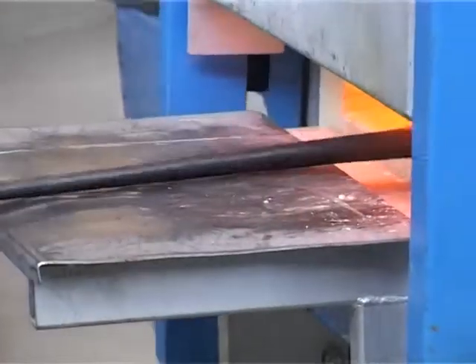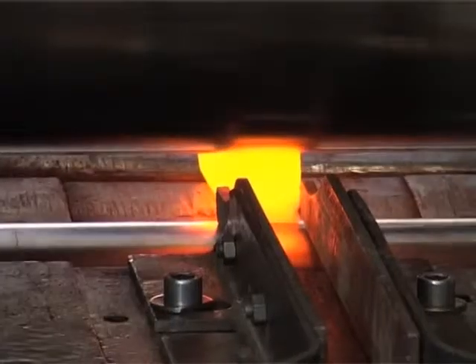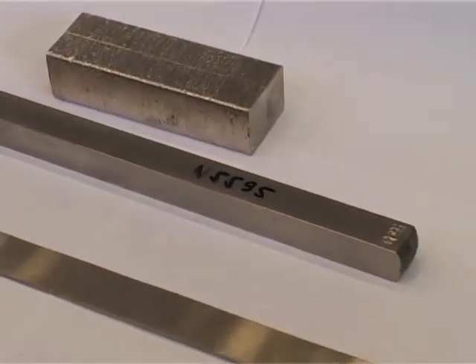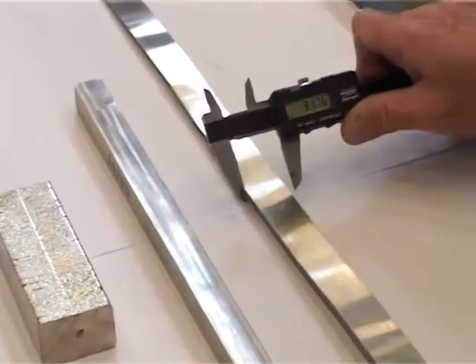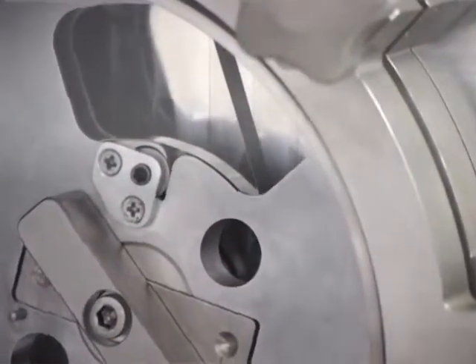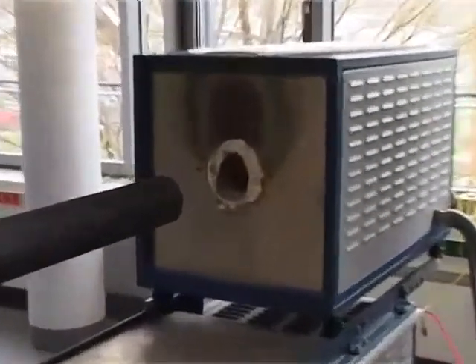After each reduction sequence, the rod must be reheated. Heated rectangular bars are rolled to lower dimensions. This long process of manufacturing flexible, high-texture nickel-tungsten tapes requires certain skills and precision. Getting very high-quality substrates for the coated conductors based on RABiTS is a very difficult task because even PPM-level inclusions can completely change the recrystallization behavior. We also need extremely smooth surfaces with nanometer roughness over long scales, obtained by these long-length heavy-industry techniques. To texture the metallic tape, we work in a reducing environment using forming gas at 700 degrees.